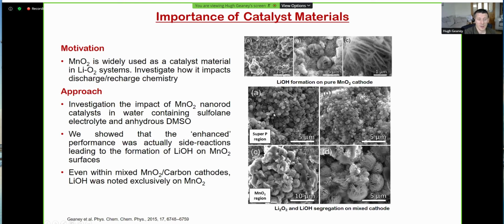But what we found really interesting was that it was actually specific to the surface as well. So within a mixed cathode where we had Super P, which is just carbon, and a manganese oxide region, we had preferential formation of these lithium hydroxide deposits on the manganese oxide regions, whereas on the Super P regions, we were only forming these spherical or toroidal lithium peroxide deposits.